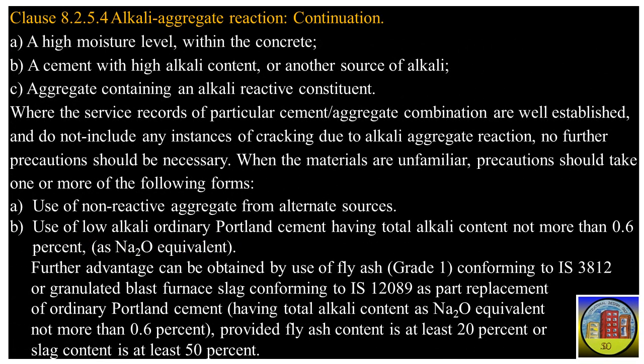This slide is a continuation of Clause 8.2.5.4, titled Alkali Aggregate Reaction, which is part of Clause 8.2.5 Mix Constituents. A. A high moisture level within the concrete. B. A cement with high alkali content, or another source of alkali. C. Aggregate containing an alkali reactive constituent. Where the service records of a particular cement/aggregate combination are well established, and do not include any instances of cracking due to alkali aggregate reaction, no further precautions should be necessary.